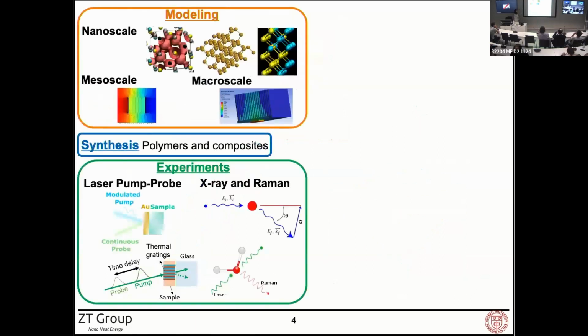In my group, we combine modeling and experiments to study phonon transport. On the modeling side, we have been heavily focused on nanoscale modeling, including DFT calculation, molecular dynamics, atomistic Green's function. And at mesoscale, we are doing Monte Carlo simulations and finite element at the macro scale. And for experiments, we have 2 custom-built setups in our lab to do the laser-based pump-probe technique. This gives us the capability to measure thermal conductivity cross-plane and in-plane for nanostructured materials.